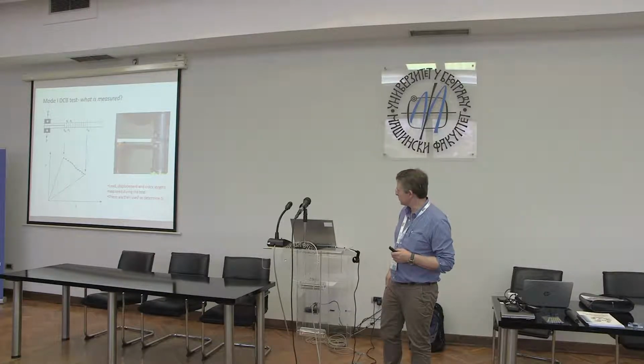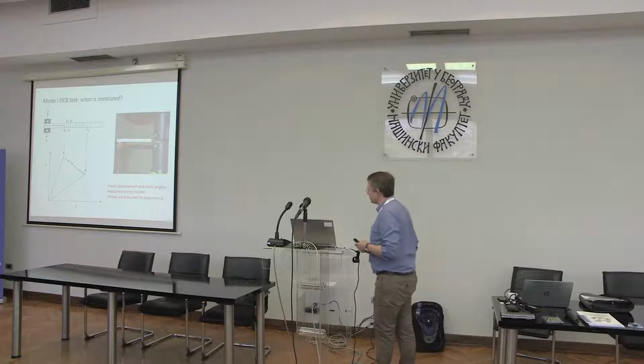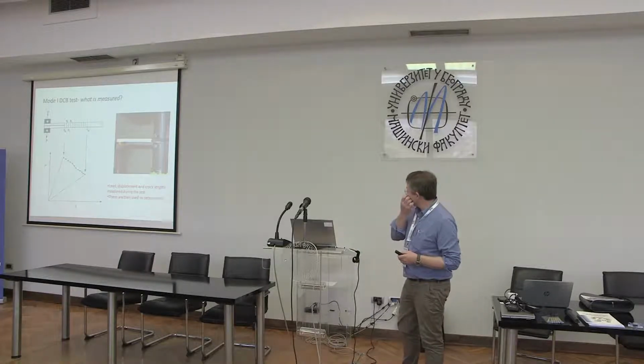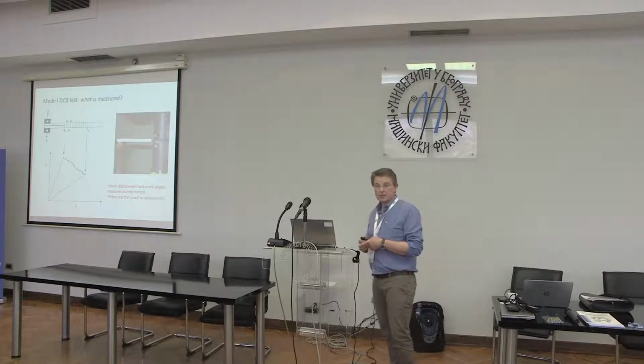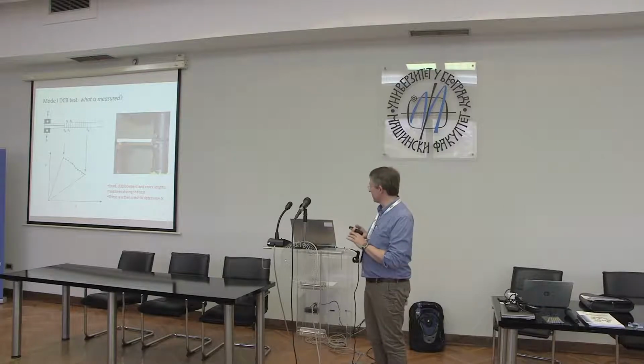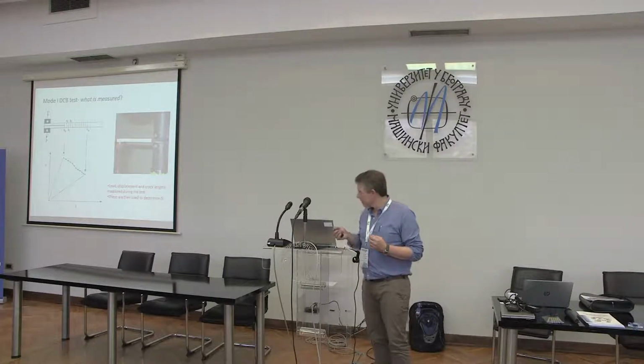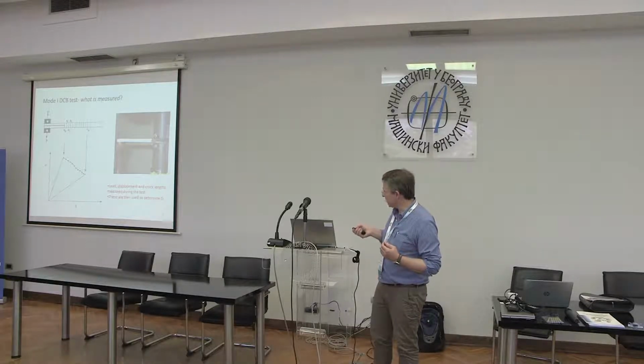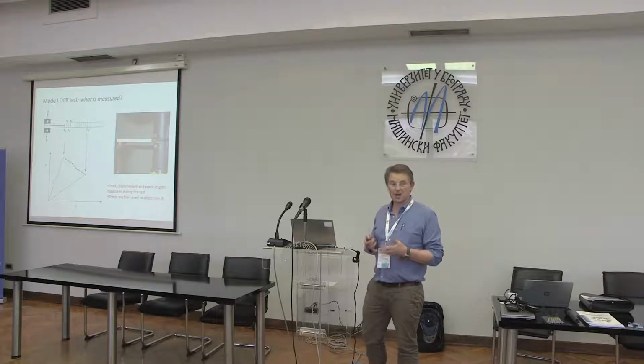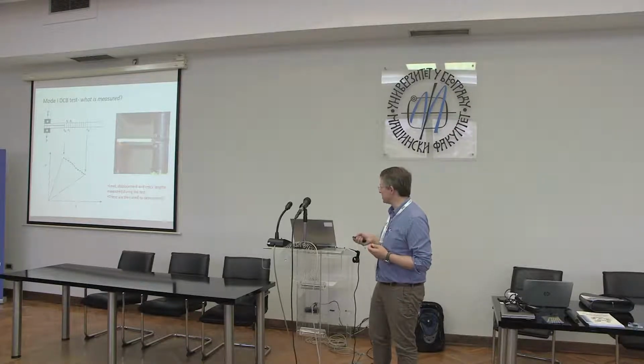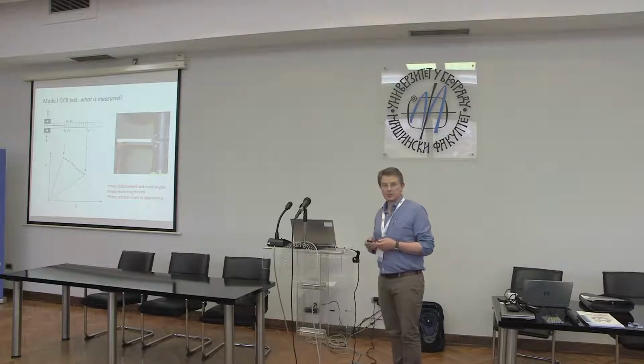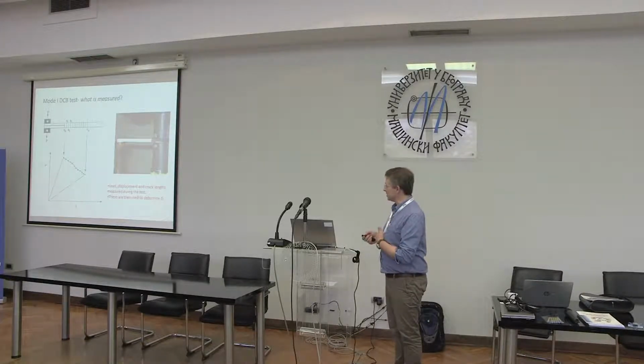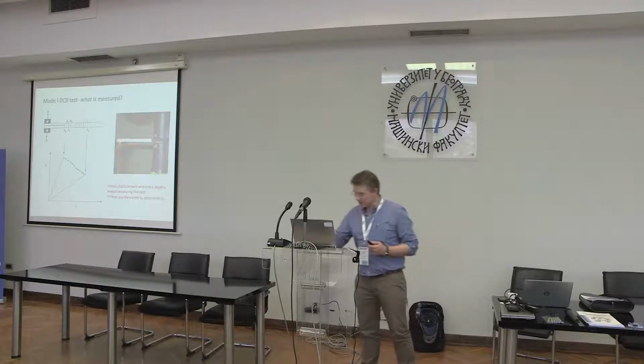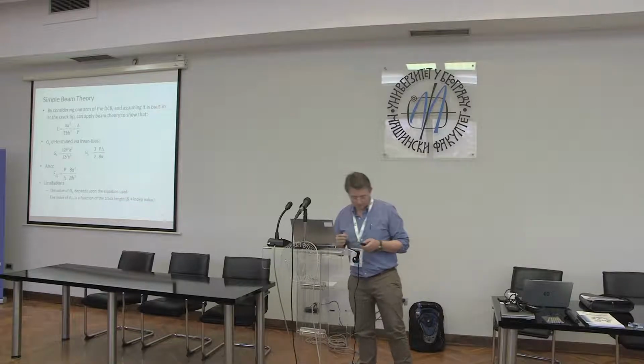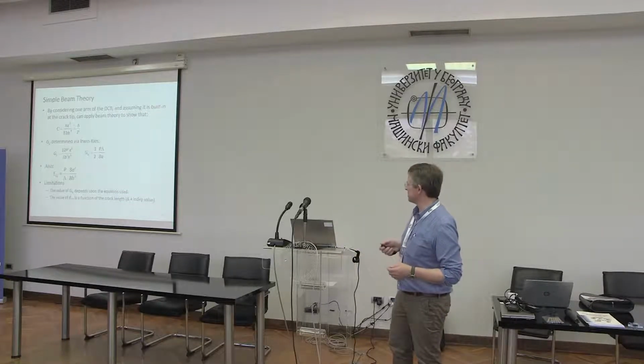This is a test specimen on the right on our Instron machine being pulled apart from its initial crack length. And of course you can draw lines on the side of the specimen, and you can monitor the crack length versus load versus deflection. And schematically, if the specimen has carbon fibers, for example, in the longitudinal direction, the system is highly linear elastic, and you can see very nice linear elastic loading, unloading profiles from the specimen, from which you can very accurately determine the energy dissipated to grow a crack through a unit distance. So it's a very nice test. And you would think that there would be absolutely no problems with it. Of course, that is always not the case.